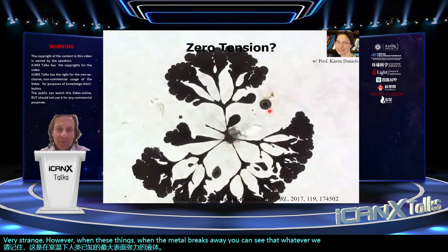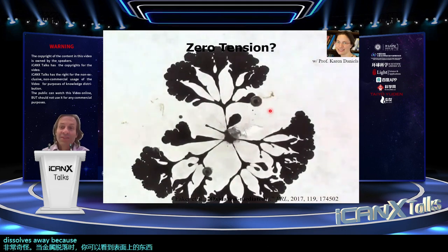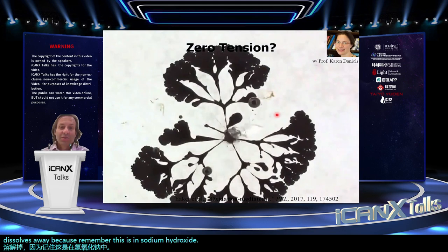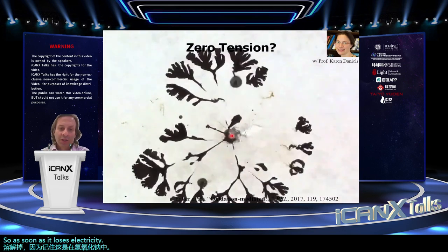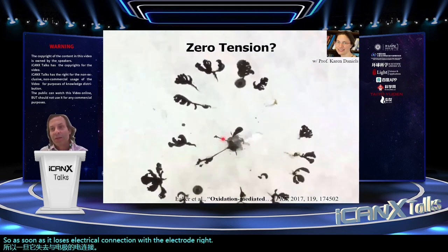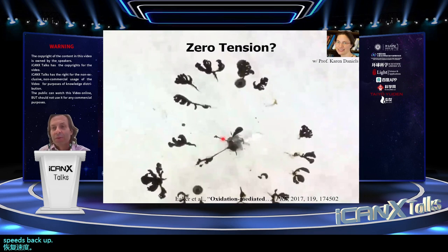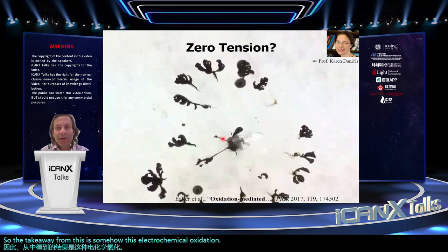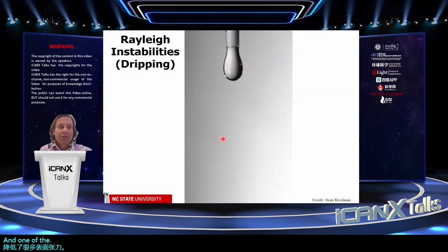However, when the metal breaks away, you can see that whatever was on the surface dissolves away, because remember, this is in sodium hydroxide. So as soon as it loses electrical connection with the electrode right here, it just beads back up. So the takeaway from this is somehow this electrochemical oxidation, not just regular oxidation, electrochemical oxidation, is lowering the surface tension a lot.